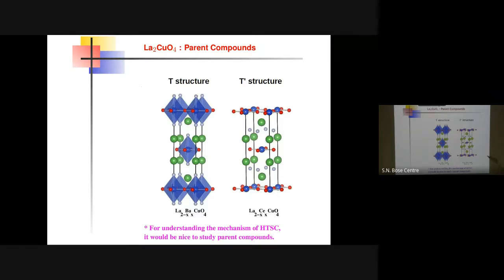So hole doped are of one structure, and electron doped is of another structure. Structurally, there is a certain difference. In case of the T structure, there is this copper oxygen plane, but there is this out of plane oxygen, and that sits just above the copper atom. In case of the T prime structure, this oxygen changes its place, and instead of sitting just above the copper, it shifts and sits above the oxygen in the plane. That's all that has happened, nothing more.